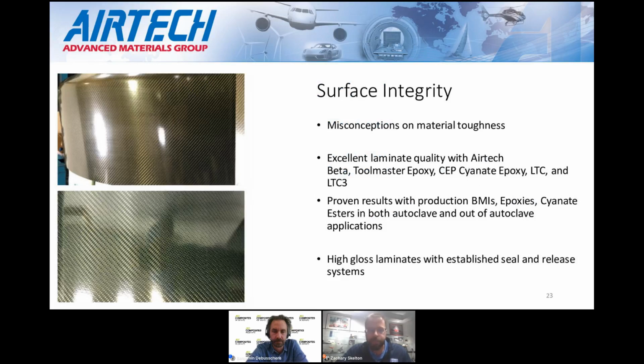And again, looking at that surface integrity. Like I said, there's some misconceptions on the material toughness, but we have been pulling laminates from that tool. You can see a couple examples there, benzoxazine and an epoxy down there at the bottom. Obviously, we've tested everything that we have in our inventory. No issues there, but we've also been pulling production resin systems off of tools, just showing that they will work. That includes BMIs, epoxies, cyanate esters, in-autoclave and out-of-autoclave applications. And like I said, if we haven't tested it, we're more than happy to go test it. But you can see just an example of the gloss that can be achieved coming off of the molds.